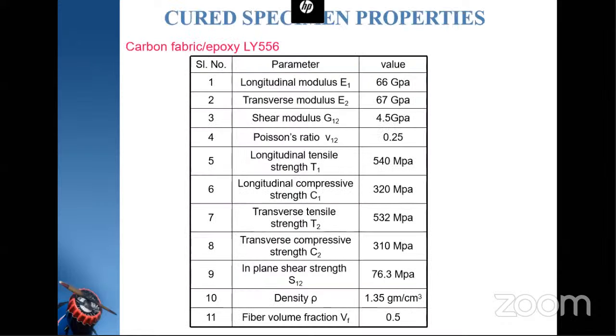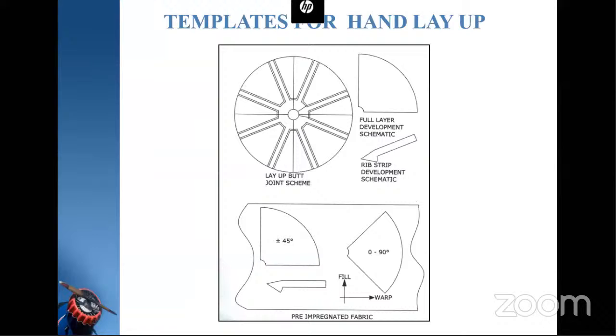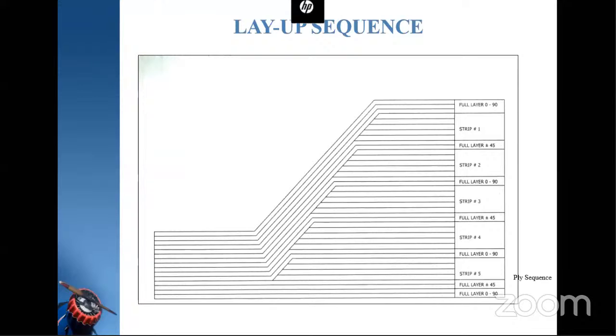These are the properties of the components which we have evaluated by making the laminates. Here you can see longitudinal modulus, transverse modulus almost the same, shear modulus, Poisson's ratio, then longitudinal strength, compressive strength, transverse tensile strength, transverse compressive strength, in-plane shear strength. Then these are the developments which we have used for realization of this component. These are the layer sequence, different layers, and rib thickness also we have shown here.